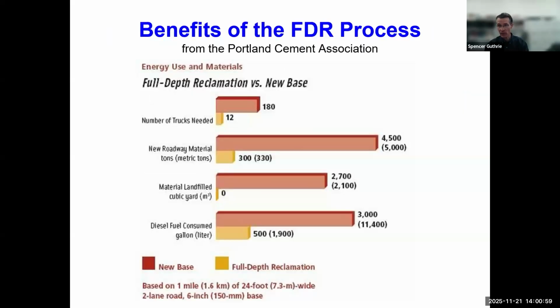Let me show you some quantitative benefits. These come from the Portland Cement Association, and they compare 1 mile of a 24-foot wide 2-lane road with a 6-inch base. Full depth reclamation, shown in the yellow bars, and a traditional reconstruction, shown in the red bars. As you scan down the chart, you see that for full depth reclamation, we need far fewer trucks. We need far less new roadway material. We contribute far less material to the landfill, and we consume far less diesel fuel. So there are a lot of advantages from an energy perspective, from an overall environmental perspective, an economics perspective, to the use of full depth reclamation.